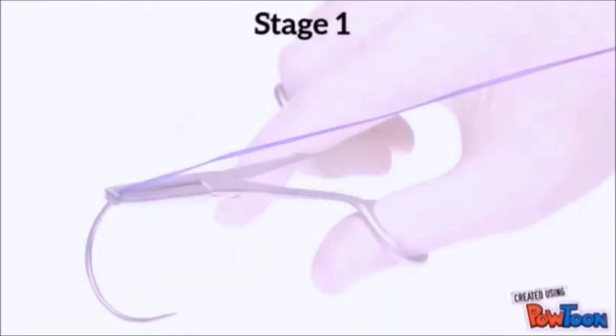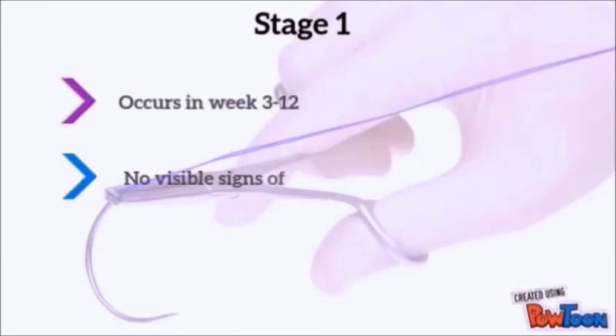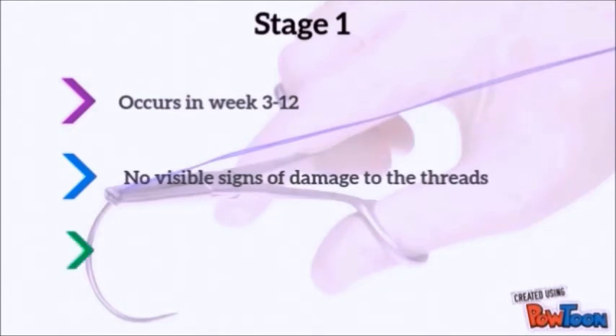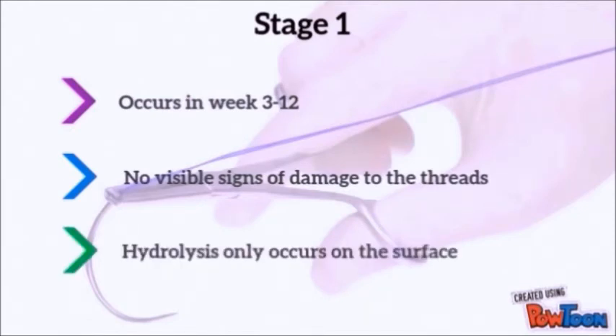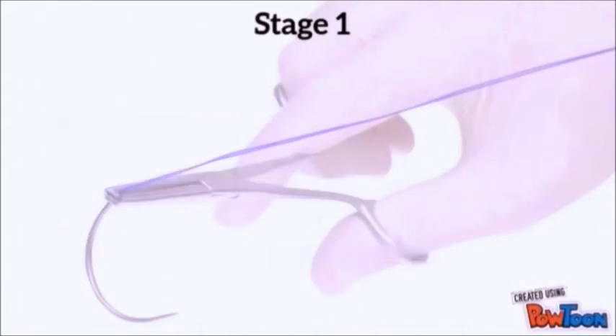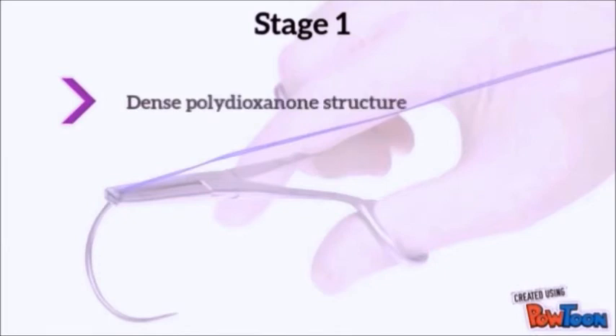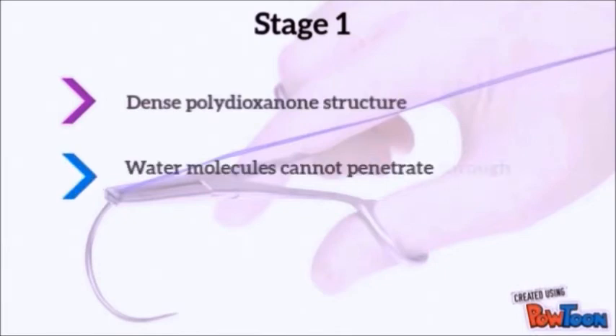Stage 1 occurs in weeks 3 to 12. Now here there are no visible signs of any damage or cracks on the filament surface, even though it's lost 9% of its weight. Now this implies that during the first 3 months, the polymer hydrolysis occurs only on the very top surface. In this stage, the slow rate of hydrolysis occurs because the polydioxanone structure is so dense that during the first few weeks, the water molecules just cannot penetrate through it.